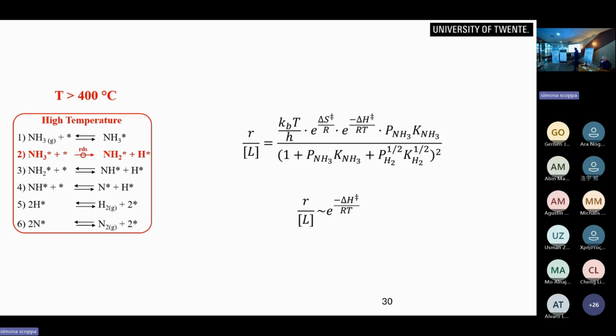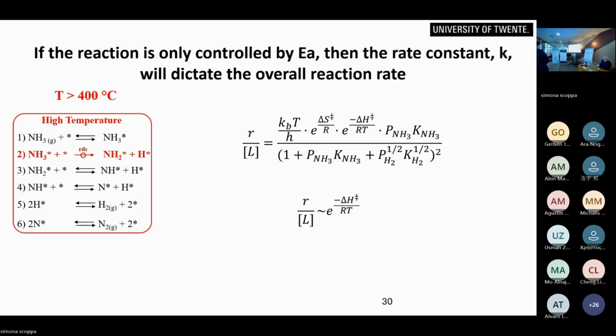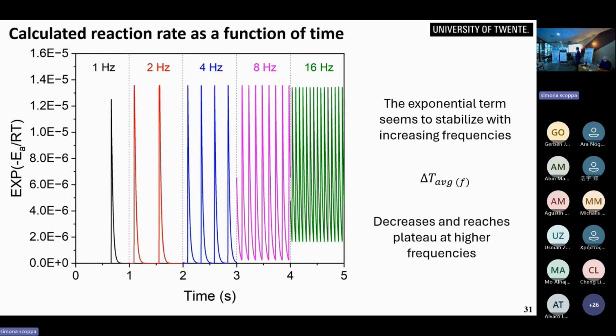And if that was the case, then if I write down, using transition state treatments, the reaction rate expression for this process, it boils down to this rate equation that you have here. Assume that reversibility is not such an issue. And you see here that this term, this is essentially your Arrhenius term, should increase the higher the temperature goes. And so if that is true, then the reaction will be exclusively controlled by how high I go in the peak. And so I can assume that this is a typical activation barrier, and I can see what is the value of that exponential term.